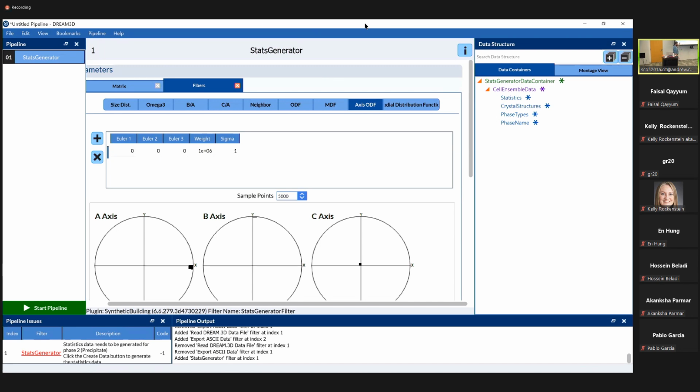So this weight value is related to the number of bins. If you want to make sure that this texture component, one texture component, is basically the only texture that's chosen, you need to have a weight that is at least the number of bins, because the weight is normalized by how we discretize the space.